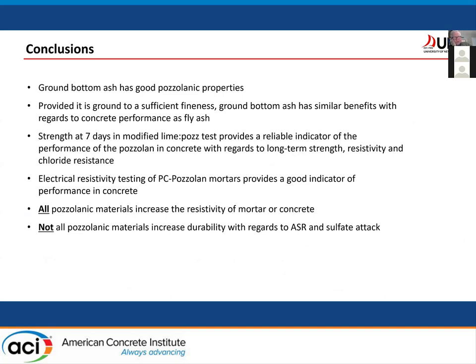So in conclusion, bottom ash, when it's ground up, has good pozzolanic properties. When it's ground to sufficient fineness, it's similar in terms of its benefits regarding performance to fly ash at the same replacement level. This modified 7-day lime pozzolan test is a reliable indicator of performance with regard to strength, resistivity, chloride resistance and other properties, and electrical resistivity of these mortars provides a good indicator of performance in concrete. All the pozzolanic activities increase resistivity, but not all pozzolanic materials increase durability with regards to ASR and sulfate. And that's another indicator of whether something's doing something useful or not.